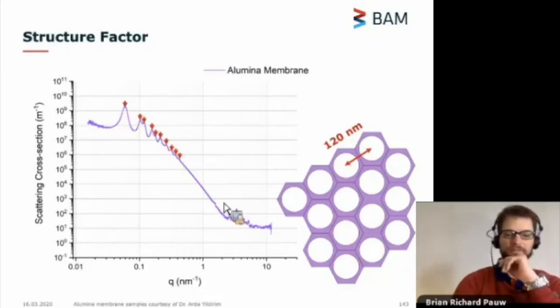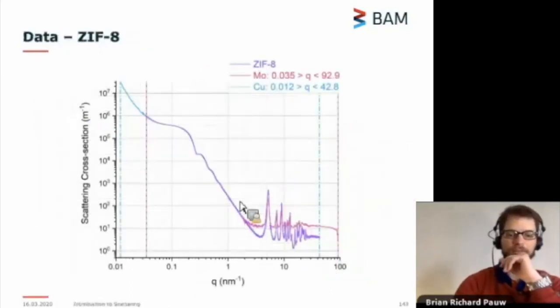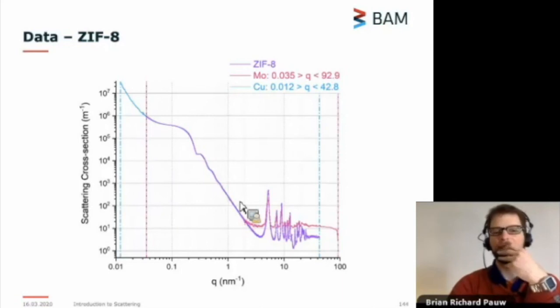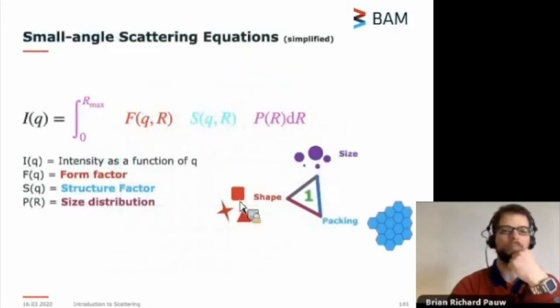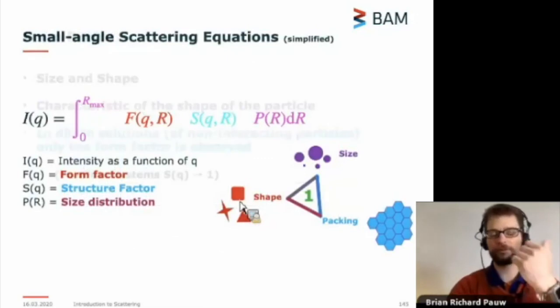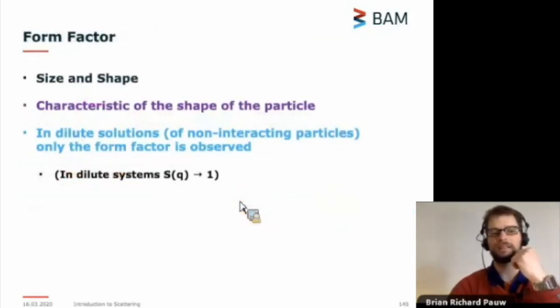What else can we see over here? Well, in the small angle region, we see this. This is not diffraction. These are not peaks. These are bumps. They are different. These bumps come from the form factor of our sample. The form factor is characteristic of the shape of the object and, to a lesser degree, of the size.